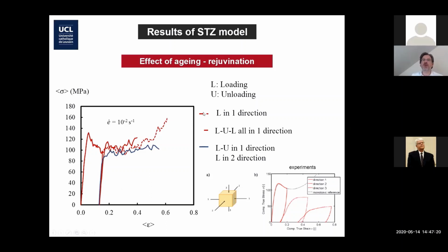Before I move on, I just want to mention this. This is a compression simulation where you go from the peak stress, you have the softening, and then the rehardening. If you unload after 20% or 50% and you reload, oops, sorry, you see that the peak stress is now much smaller. Basically, you have what is called in polymer science rejuvenation, meaning that after a deformation step, you have put excess energy into the material, and you have reduced the stress that you need to continue the plastic deformation. And basically, when we start with a mesh with no excess energy, we always overestimate the peak stress. But the reality of the polymer material is that it has not necessarily undergone a long aging. It is in a state between aging and rejuvenation.